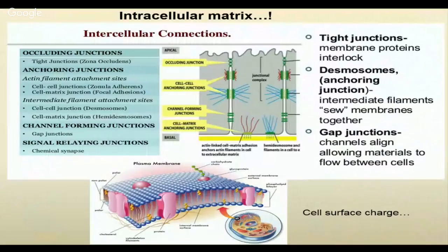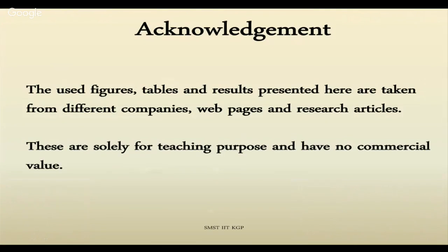And similarly, can you use any other material? Can you propose anything? Collagen, for example. Collagen has RGDs: arginine, glycine, and aspartic acid. This arginine is recognized by the cell surface receptor integrin. So simply, collagen can be coated. In the market, different types of cell culture petri dishes are available. Some of them are polylysine coated, some are collagen coated, which eventually promote cell adhesion either by the RGD receptor or by electrostatic interaction, and then we can expand the cells on the material surface. So definitely surface charge is important. I think I want to stop here.